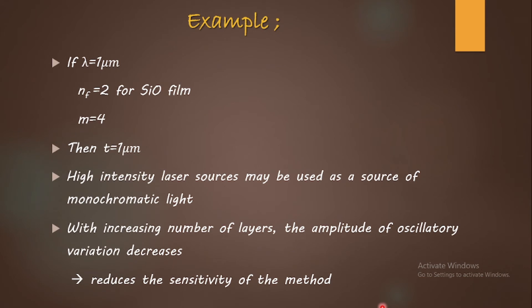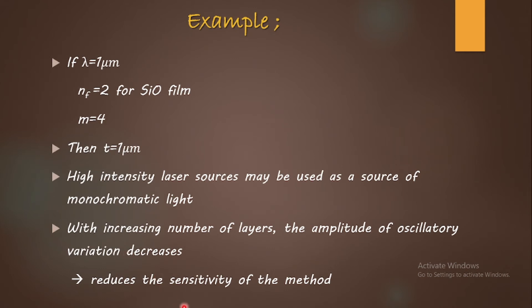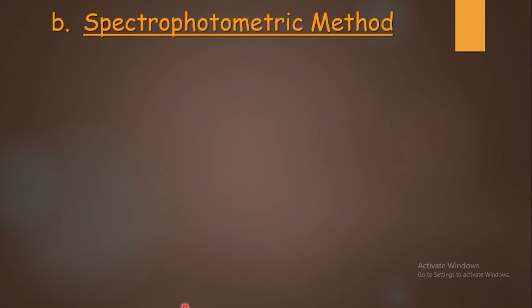To summarize the photometric method: it is applicable for dielectric and semiconductor films. Using the optical constants — wavelength, refractive index — and the formula, thickness can be easily calculated. For thicker films the sensitivity decreases, which is a limitation. The principle is interference and the key observable is the oscillatory nature of reflectance and transmittance with respect to different film thicknesses.